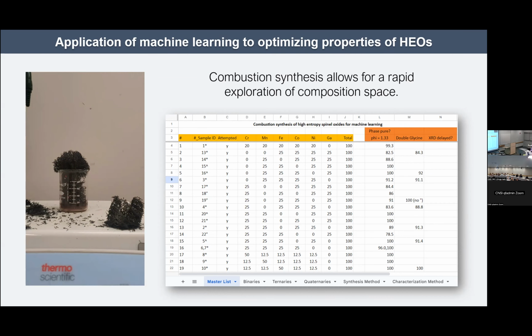But what is amazing is that this is entirely real-time video. It's not sped up in any way. And that chemical reaction is taking place in seconds. There's some work that goes into preparing the solution, but the synthesis itself takes place in seconds. And once we put that product in the oven for an hour, it comes out beautifully crystalline, with very clean X-ray diffraction patterns. And so we've been able to survey hundreds of compositions at this stage, which I hope to come back to a future ICAN meeting and tell you about the results of our machine learning efforts.